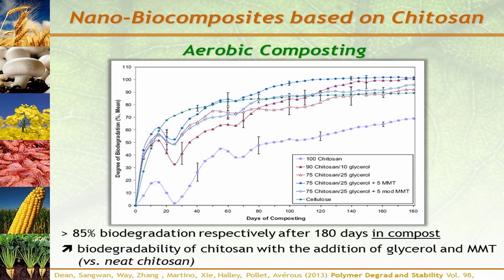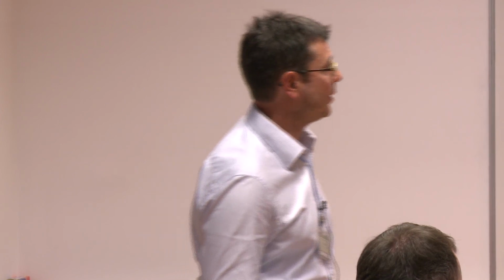And finally, to conclude, we have also tested the biodegradability and the aerobic composting of this material. And you see that 95% biodegradation is achieved after 180 days in compost. And that compared to neat chitosan, the addition of glycerol and clay lead to a slightly enhanced biodegradability of these materials.